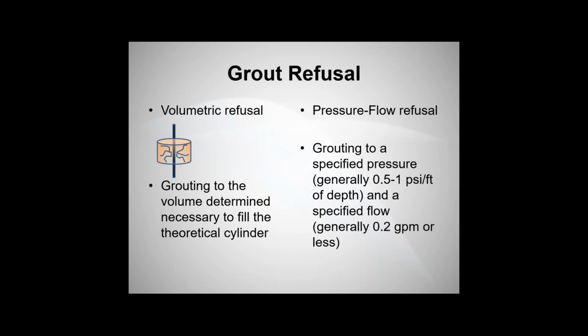You'll also have a pressure flow refusal, similar to rock grouting. A lot of times in permeation grouting, it's going to be somewhere between 0.5 and 1 psi per foot of depth, definitely not over 1 psi, and a specified flow rate, which I have as 0.2 GPM here. Realistically, you're probably at 0 as your flow rate for a grouting refusal on a permeation grouting job.